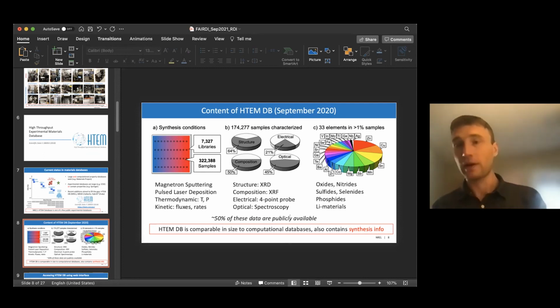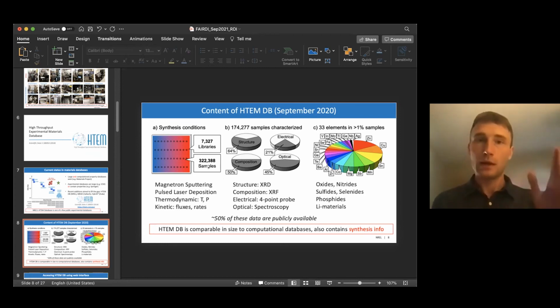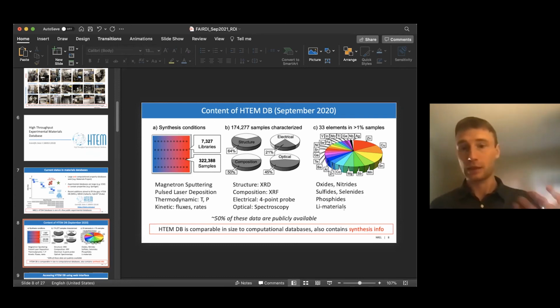You mentioned already how the synthesis conditions affect different properties. The other maybe hidden variable here is how the off-stoichiometry affects the properties, right? We often make these compositionally graded sample libraries where stoichiometric material, let's say, is in the middle and there's an off-stoichiometry on the left and the right. How exactly off-stoichiometry influences the properties, in particular electrical properties, and how it leads to self-doping of the materials is something that is extremely difficult to capture computationally. And I think these types of more subtle synthesis-property relationships and various non-idealities, including kinetic synthesis conditions, as well as effects of off-stoichiometry on materials properties, are a big added value.